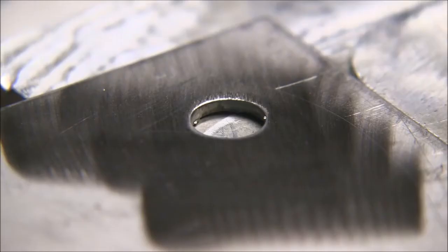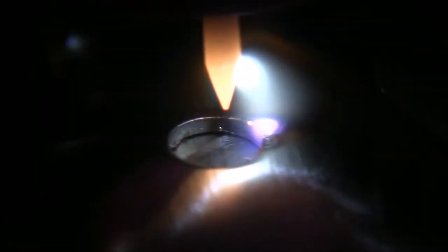This is an 18 gauge stainless steel 1/4 inch hole that I would normally fill up, and I could easily use a 3/32 electrode, but watch the start on this. Never does go out to the tip, even at that low amperage. Doesn't reach the tip of the electrode, just goes off to the side. It actually melts the metal on the corner of the hole that's drilled there, but doesn't go accurately.